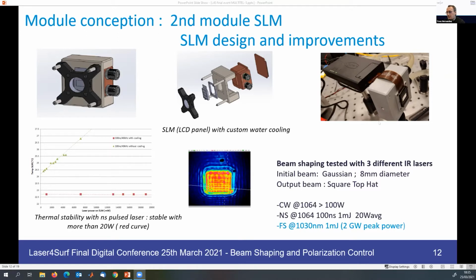You have a picture of the SLM on the top, and with this construction, we were able to use the SLM up to 100 watts in CW mode. In nanosecond, we can reach 1 millijoule per pulse, and as well in femtosecond, 1 millijoule and 2 gigawatt power. So we had, let's say, more than enough power handling with this system for the applications targeted in the project.